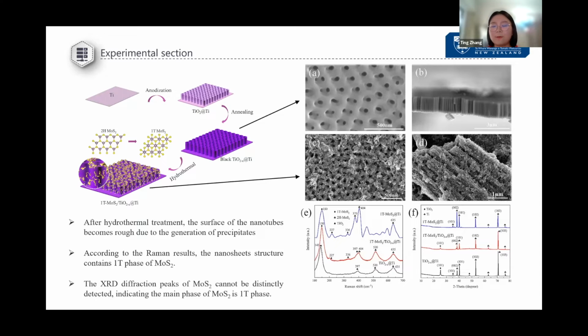nanotube itself. It is a really unique structure, because by using this structure, the nanotube array substrate can provide more surface area for the decoration of MoS2 nanosheets. Then during the HER reaction, more active sites can be exposed, which can enhance the HER property of the catalyst.